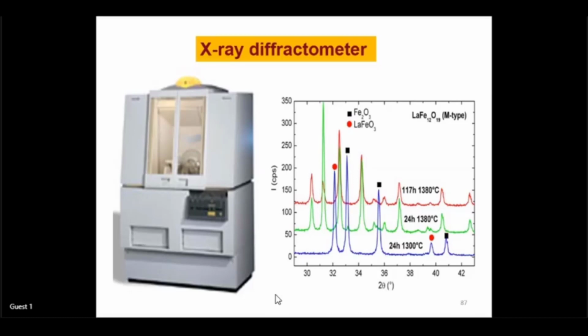So if you have an impure phase or secondary phase, then this material cannot be used for application. So you refine your method to get the pure phase. This way we can test the structural property and phase purity of the material. In this material, it is not pure M-type hexaferrite, but it has two different secondary phases, Fe2O3 and LaFeO3. So if you want to remove these two phases, you have to modify the preparation technique.